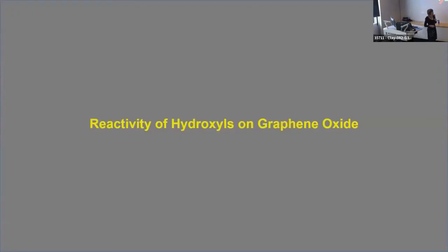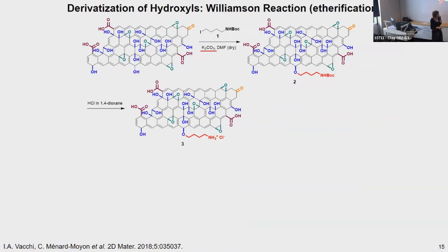So now that we have investigated the reactivity of the epoxides on graphene oxide, we studied different reactions to derivatize the hydroxyls on the material. And the first reaction is the Williamson reaction, which is an etherification reaction, allowing to form an ether bond here. So this reaction takes place between the hydroxyls on graphene oxide and this iodinated compound in the presence of a mild base, potassium carbonate.